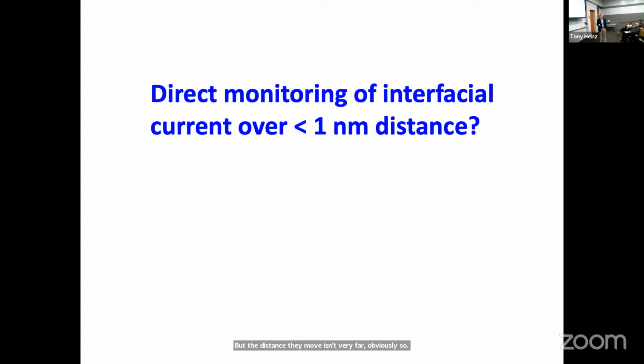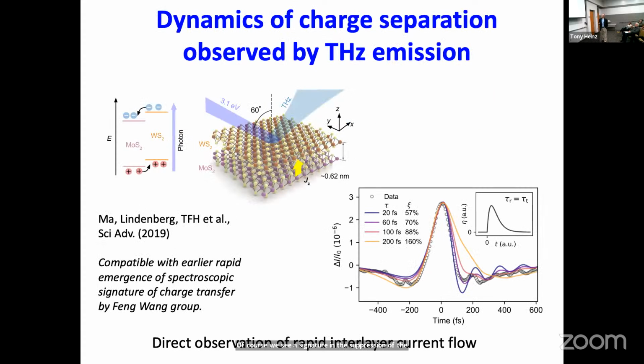So of course, we see a signature in the suppression of the emission, but is there a way we can look at it directly? And it turns out by using pulsed excitation, so you set this all up at once, you then get a quick current flow. And interestingly enough, you can actually see the radiation from this current flow. So it's like a radio antenna, very, very short. But on the other hand, the acceleration is very high because the charges are moving less than a picosecond. That actually means that you have the very high acceleration and you have emission in the terahertz spectrum. And it turns out if you monitor the electric fields here, near field radiation, there's a quantitative relation between the electric field and the current flow. So we can see that actually the current flow occurs on a time scale of about 100 femtoseconds. And that accounts for this very dramatic suppression in the emission, the optical emission from recombination.